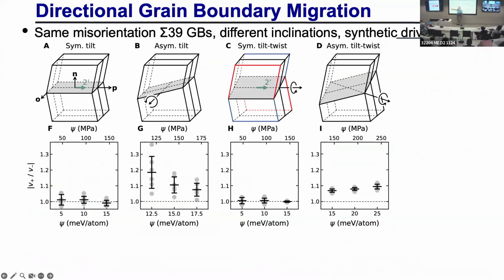And if I just look at the ratio of the velocity in the plus and minus directions, it's just 1. Typical for a symmetric boundary. That's a symmetric tilt grain boundary. If I pick a more complicated one, but still symmetric, again, you see the velocity is the same in the two directions. If I just do an asymmetric boundary, it goes like that.